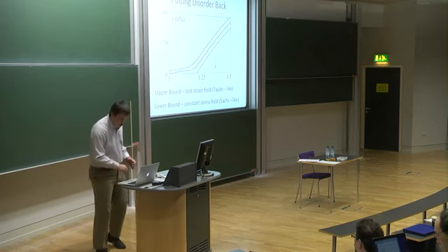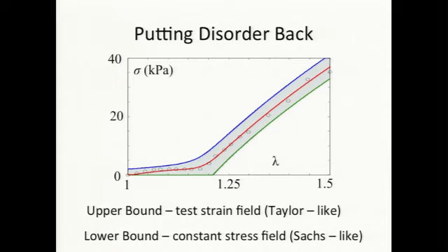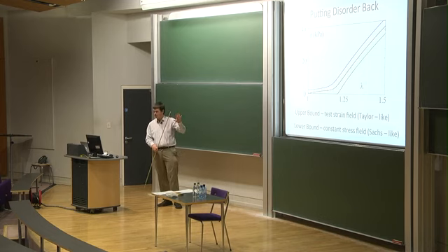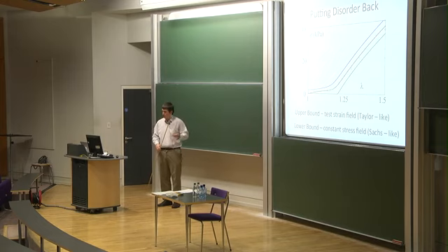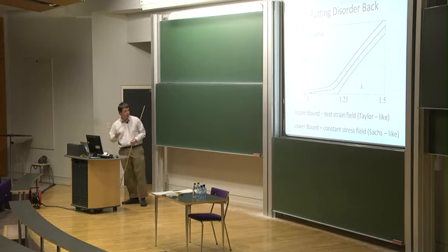Okay, so what I'm trying to say here, let's get the most important point. The most important point here is that if you have crosslinking at the isotropic state, you're completely soft. And that's really because you've got a monodomain. Right? The large dominant part of the energy doesn't have any spatial dependence. And in fact, these are probably closer to being monodomains than the things that in the field have been called monodomains. Right? The spatial dependence and the inbuilt anchoring of the director is weaker.